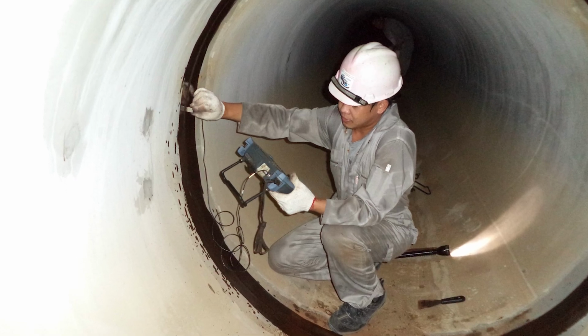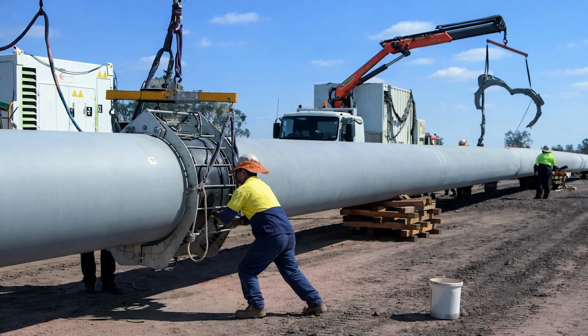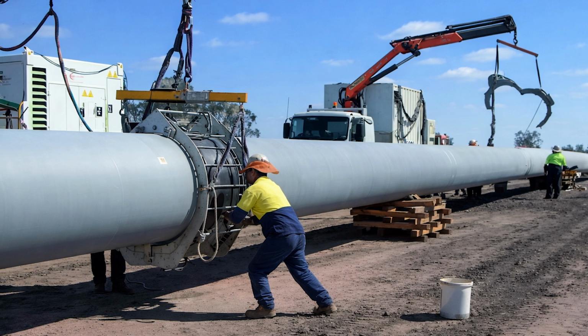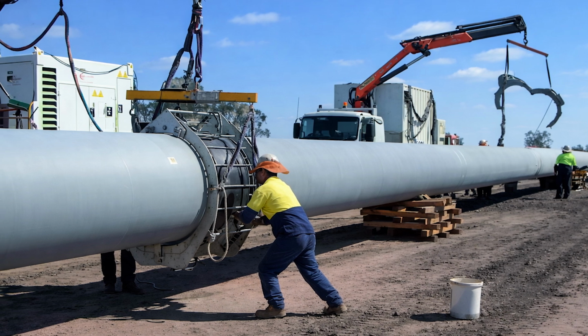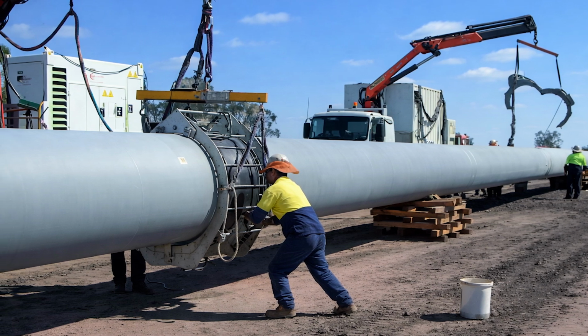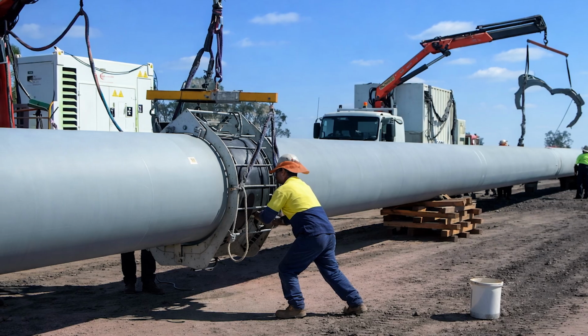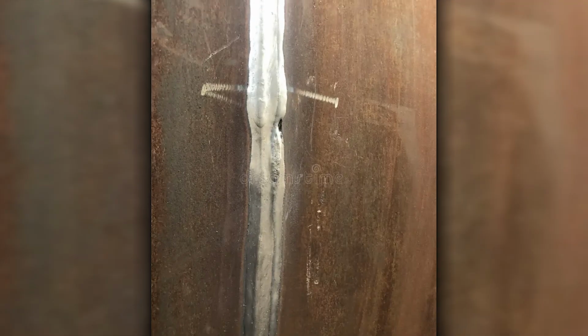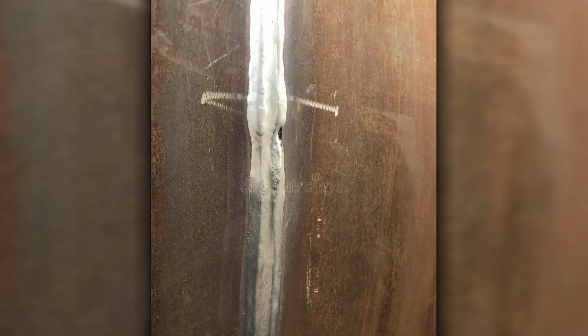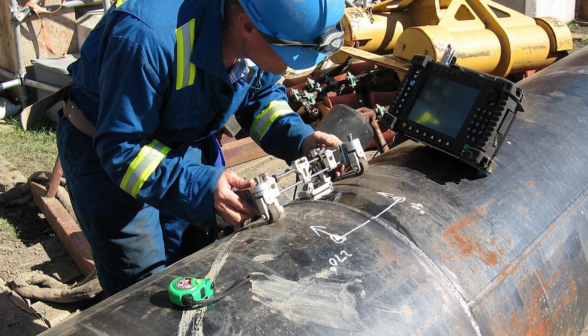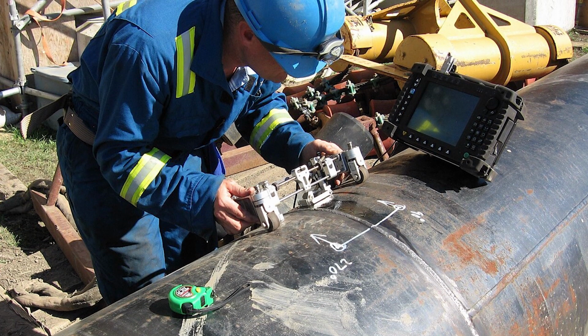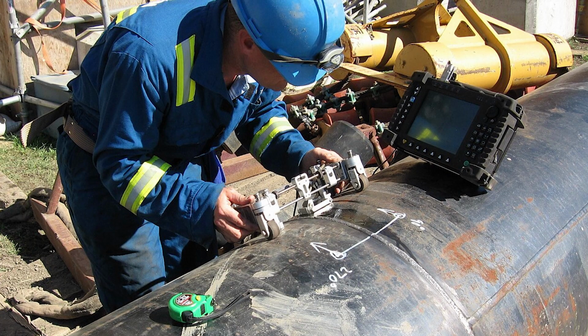Traceability binds it together. Weld maps link each joint to welder ID, UT results, and coating batch tags so a problem trend can be isolated to a day, a crew, or a material lot. Example defect pathway: lack of fusion at the root or a small coating void at the field joint edge. UT flags the former, holiday detection flags the latter, before either disappears underground.